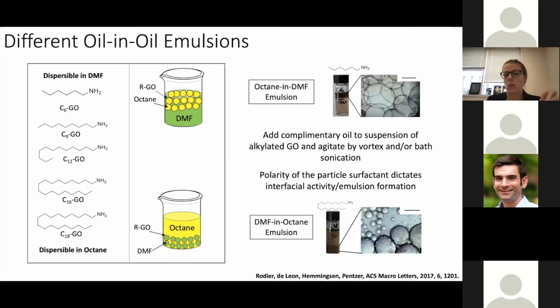And so Brad was able to show that he could form both octane in DMF and DMF in octane emulsions. So these are stable for at least 2 or 3 weeks, which is dramatically different than if you have no nanosheets present whatsoever. We've done the control experiments where we just added in the alkylamines themselves, or the protonated form of the alkylamines, and they don't stabilize the emulsions. Something to note is that the C12 modified nanosheets are actually not very good surfactants and give emulsions that are only stable for a few days.